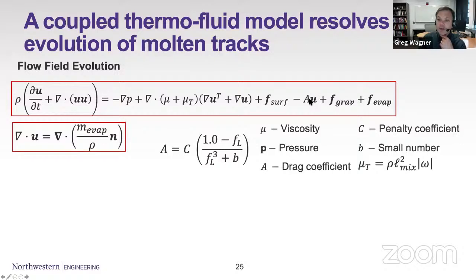We have a penalty term in the solid region that constrains the velocity to zero. This is a fairly common way of handling these kind of solid to liquid phase changes. Gravitational forces and evaporation forces then at the surface themselves. In our continuity equation, we're assuming that our two individual phases, metal and gas, are constant volume, but at the surface itself, we can have evaporation, and this leads to a volume change right near the surface. And so this is where this additional source term comes in: instead of divergence of u equals 0, we have a divergence of u equals that volume change that's happening at the surface.